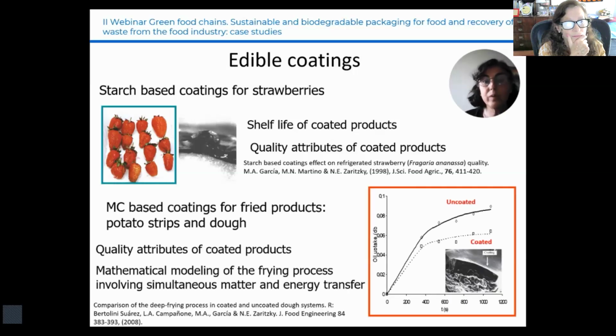Along these lines, we developed edible coatings based on cellulose derivative for potatoes and dough subject to frying. The coating significantly reduced oil absorption during frying, as shown in the graph, and maintained their integrity. In a study led by Dr. Zaritzky, the frying process of dough with and without coating was mathematically modeled, a process involving the simultaneous transfer of energy and mass.